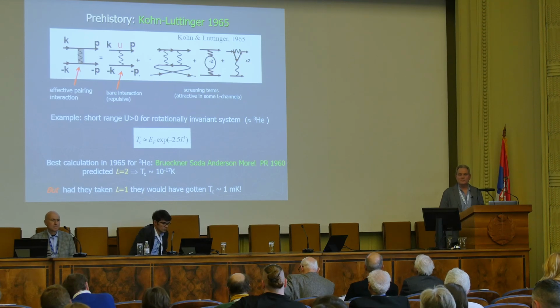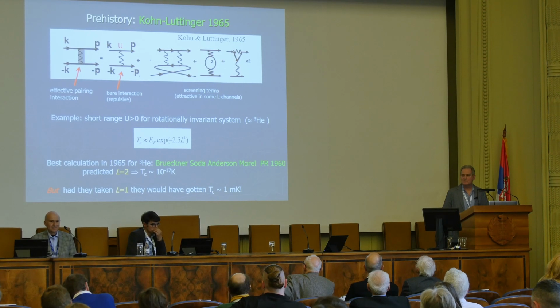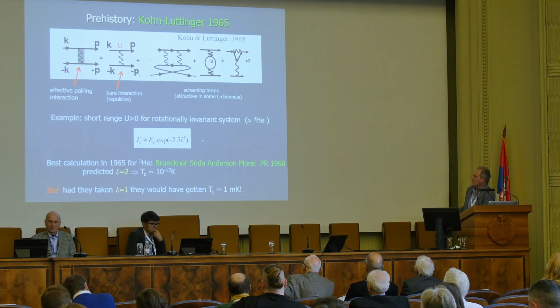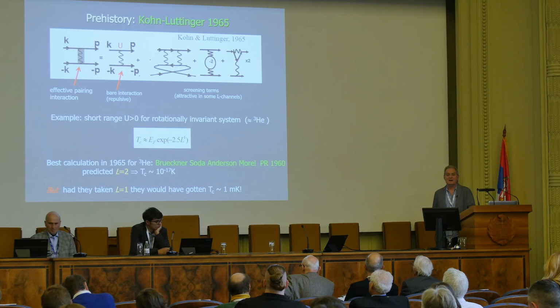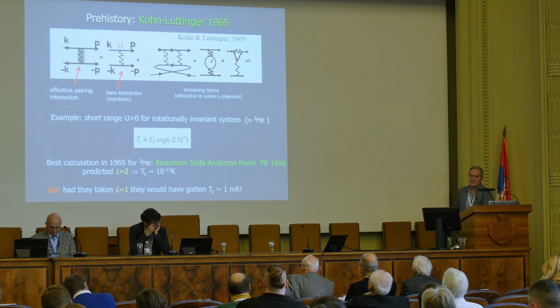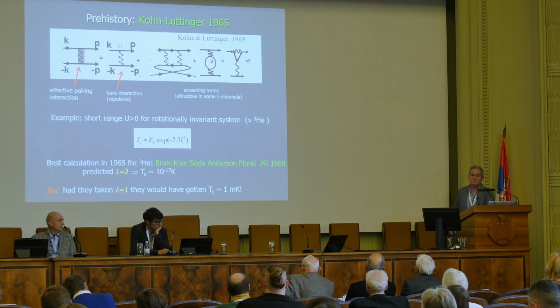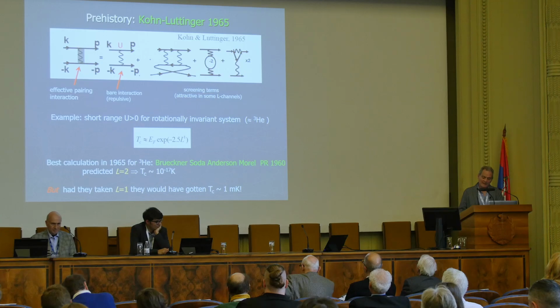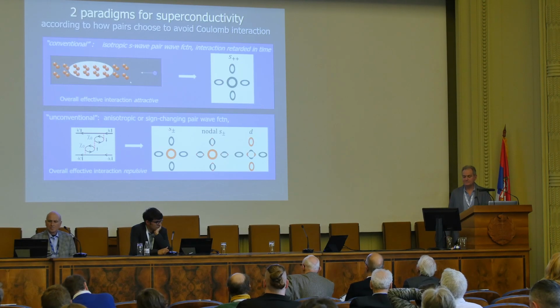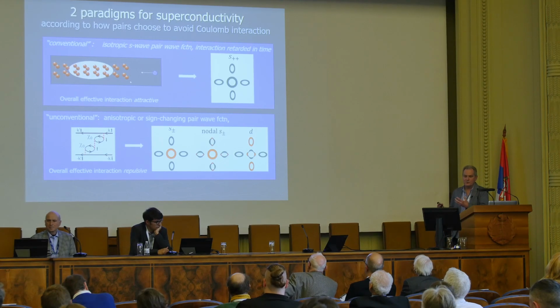So when I was a graduate student, we used to say, oh, you've discovered Kohn-Luttinger superconductivity, and that was sort of an insult because it was something that no one obviously was ever going to be able to measure. On the other hand, it turns out that there's a more complex formula for arbitrary L, which they also worked out but didn't advertise. If you put in L equals 1, which is the correct orbital angular momentum channel for helium-3, you get about 1 millikelvin, which is pretty close to being dead accurate. Probably accidentally so, but still, it's much better. So this is the idea that you can get superconductivity from repulsion in an electron gas.